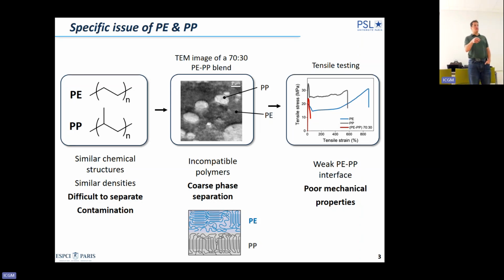Both of them are highly ductile. And if you blend these two materials, even without doing anything else, so they were not aged, they did not suffer any kind of degradation, took them from the bottom, we just blend them, you inject them to get the dog bone, and then you go from a ductile material to a fragile material. So this is an exemplification of the problem we have to deal with.